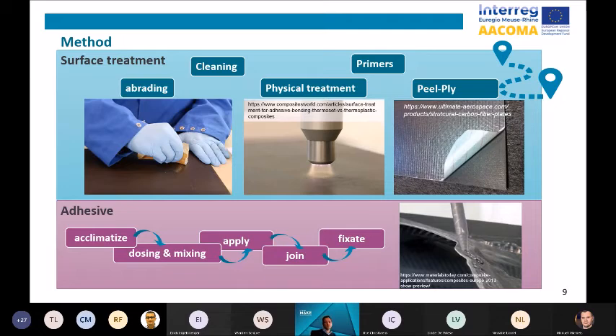One of them is abrading the surface with the goal to remove all contaminations and moisture in the top layer. And for composites, extra care is needed. Due to the hygroscopic properties of the fibers, you have to prevent that the fibers are exposed on the surface. The fibers will attract water or solvent, which can become trapped between the adhesive and the substrates.